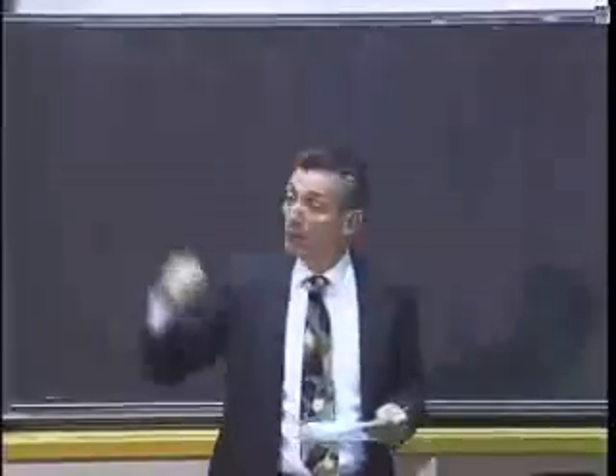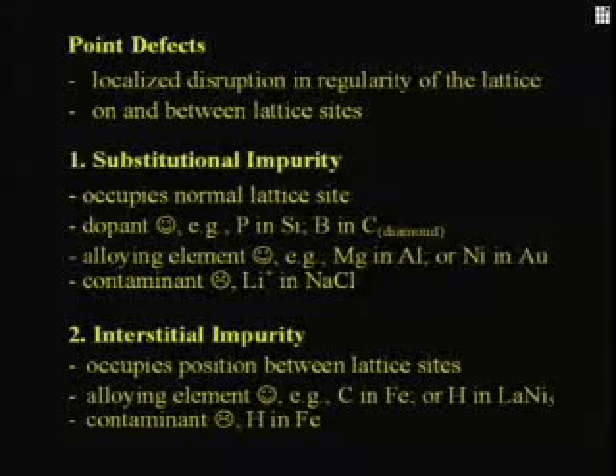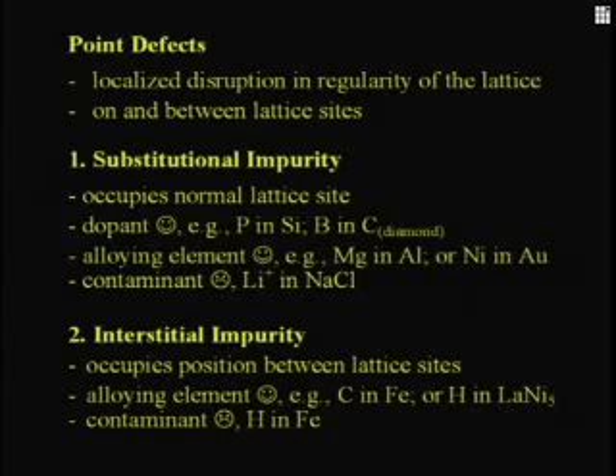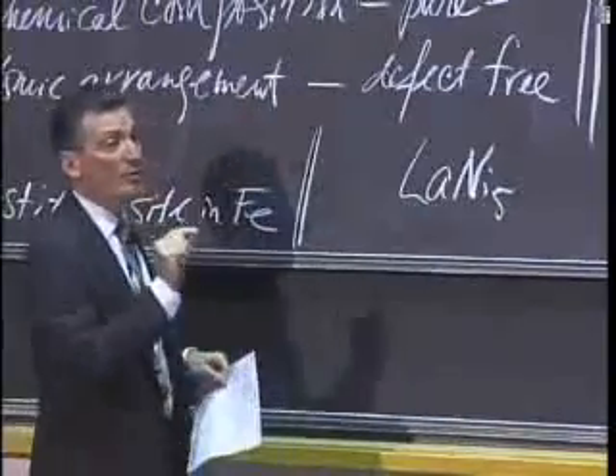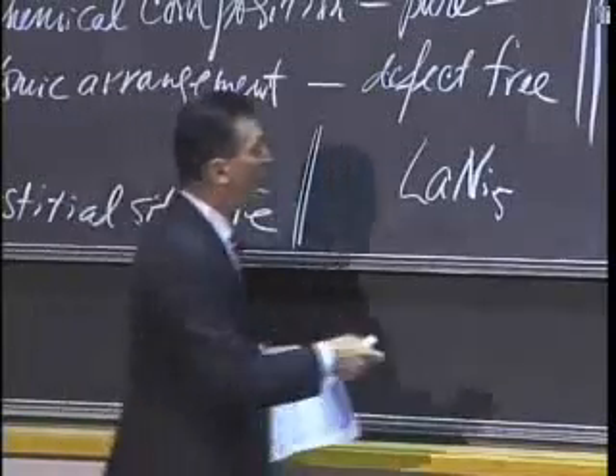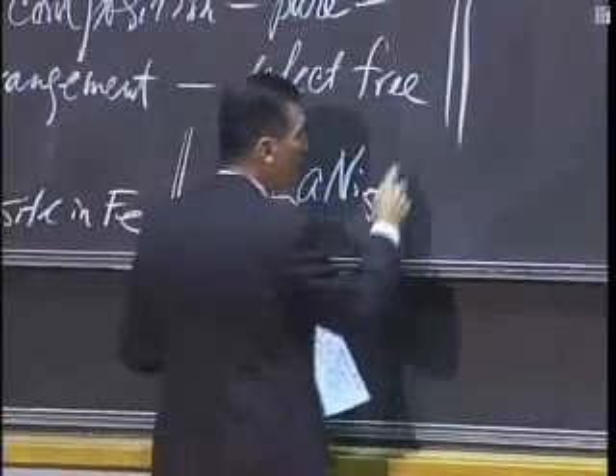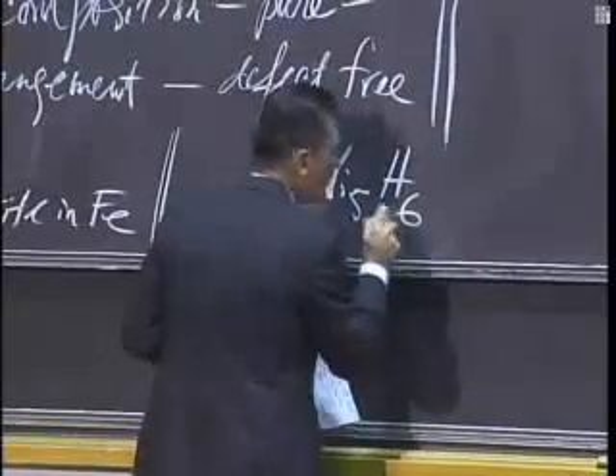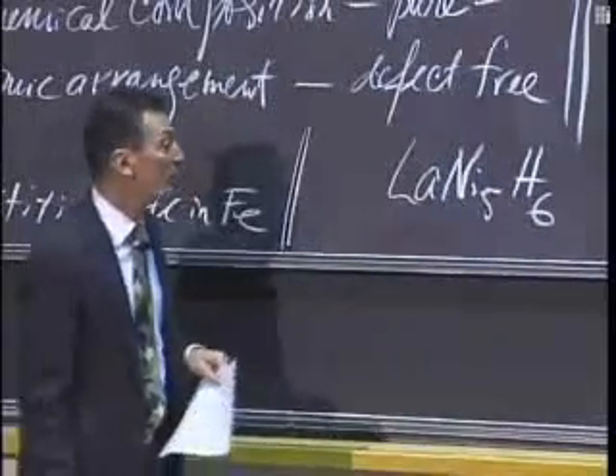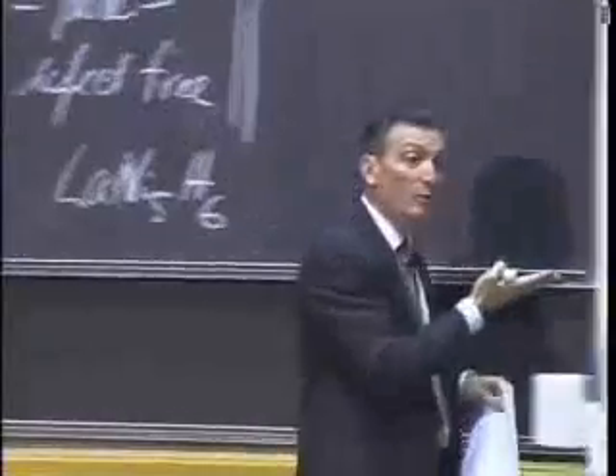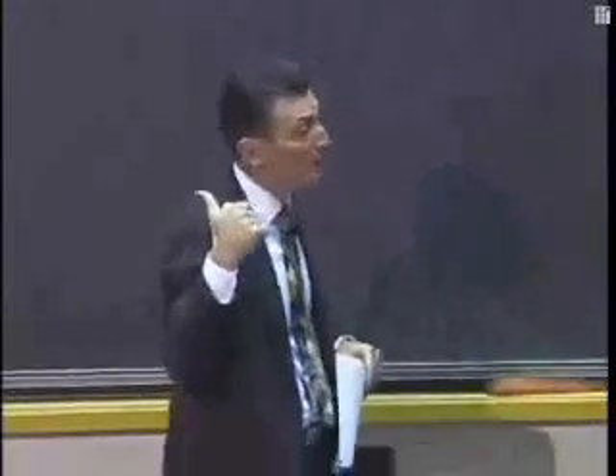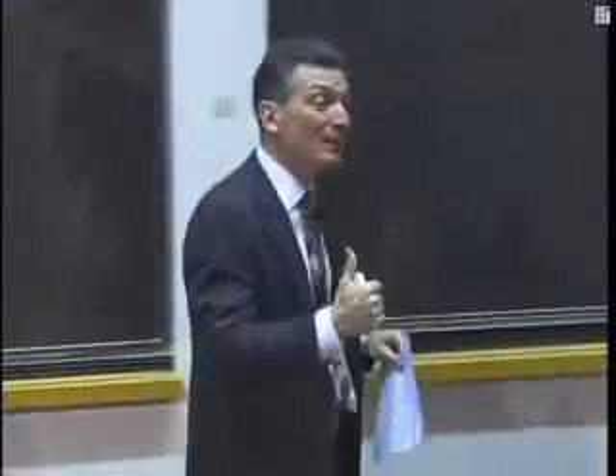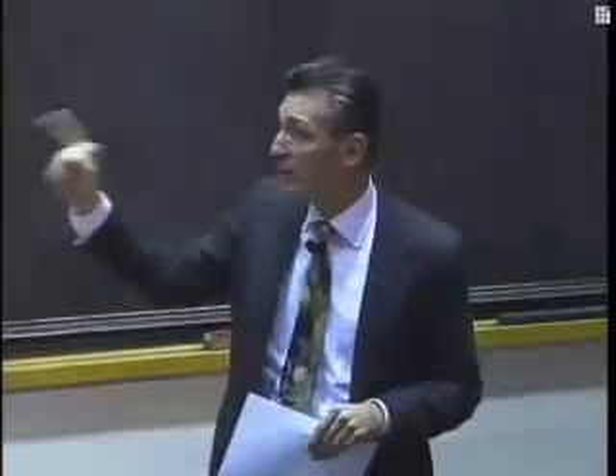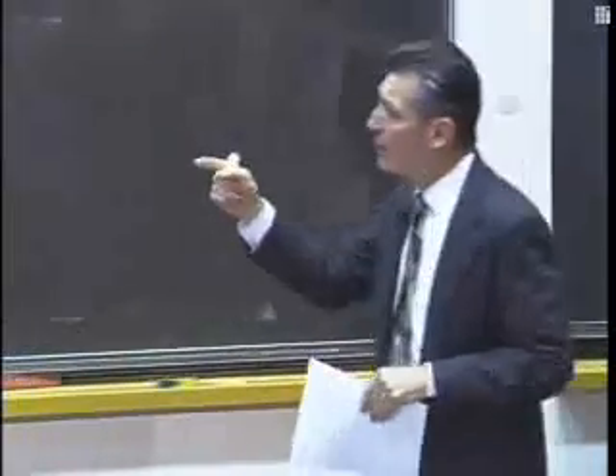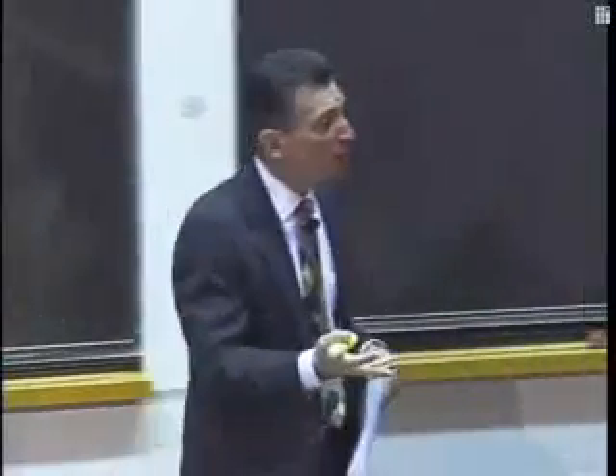Another example is hydrogen in lanthanum nickel 5. It goes into the interstices in this compound. Lanthanum nickel 5 has voids that are large enough to accommodate hydrogen. And hydrogen can go in. This acts as a sponge, and hydrogen at peak loading can go in at this level. We have a huge amount of hydrogen going in here. The density of hydrogen in lanthanum nickel 5 at saturation is greater than liquid hydrogen itself. And this material is under investigation, along with others like it, in the context of hydrogen-powered vehicles.